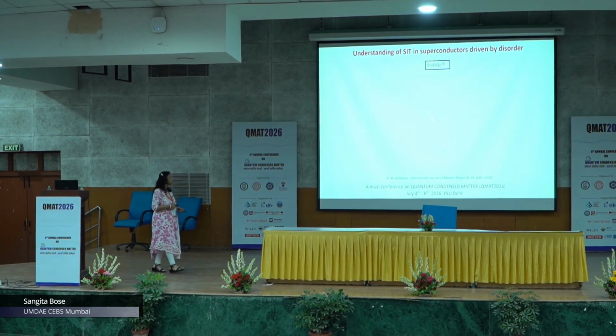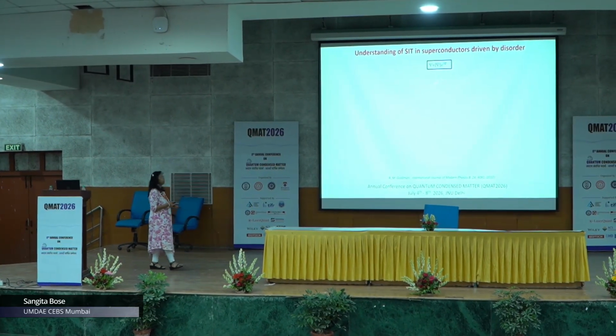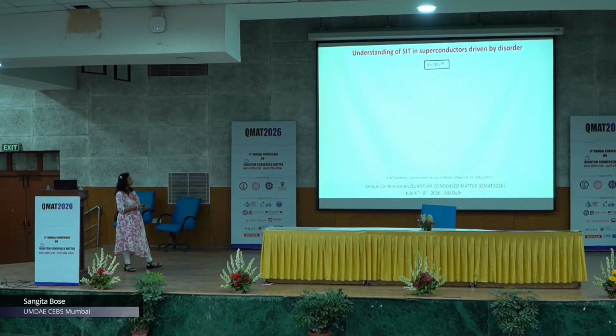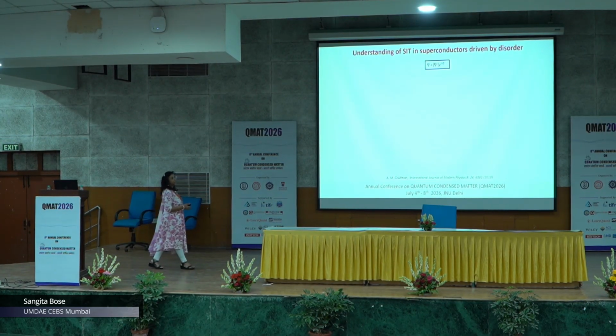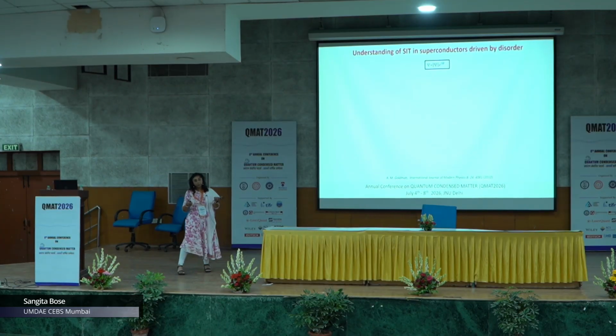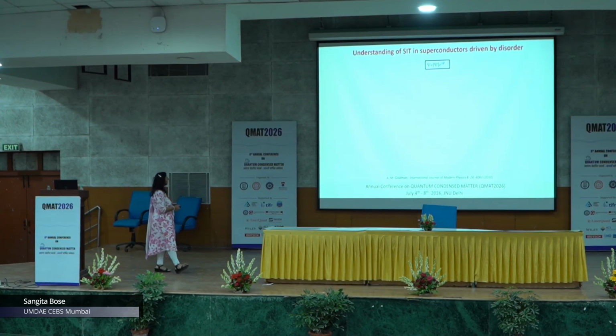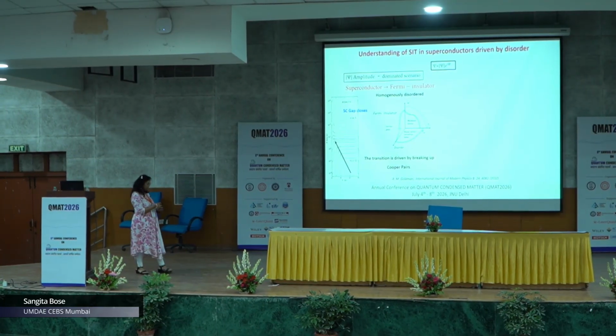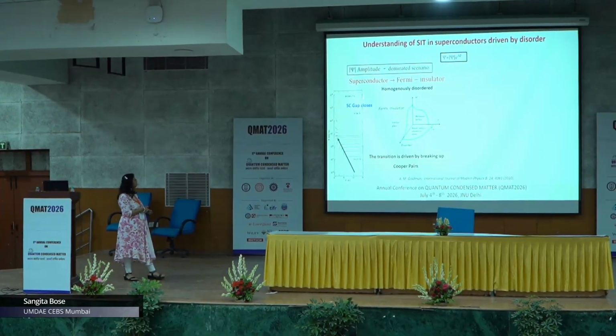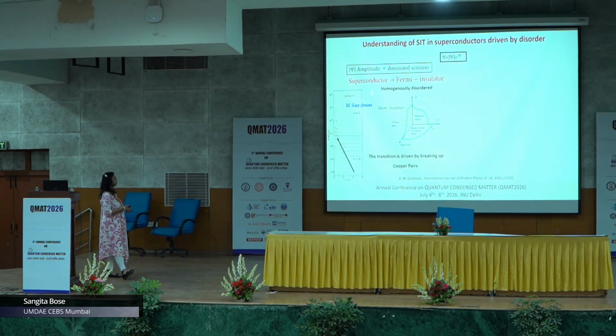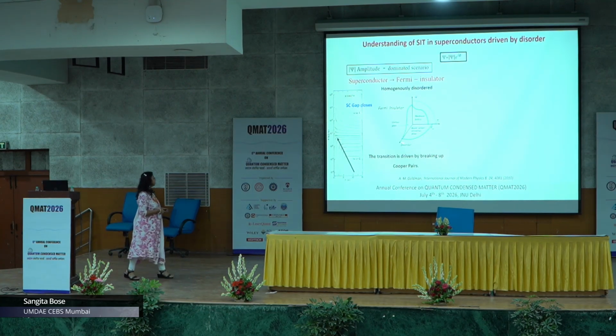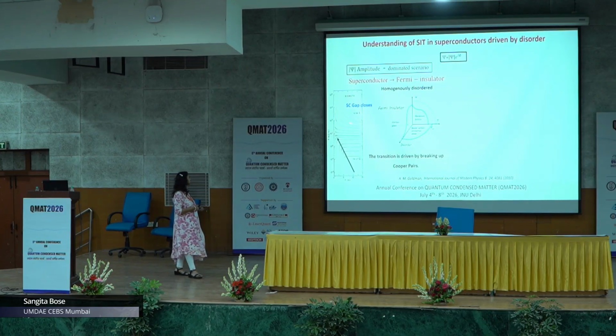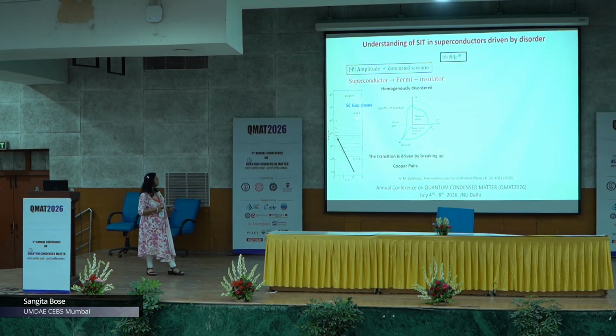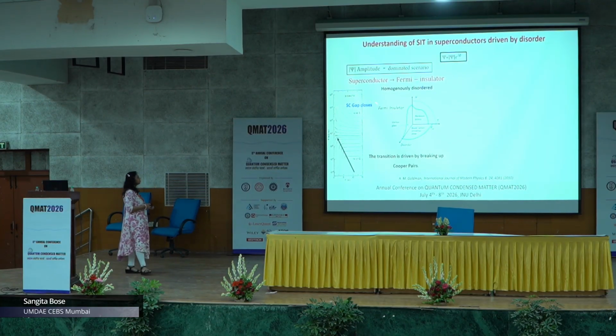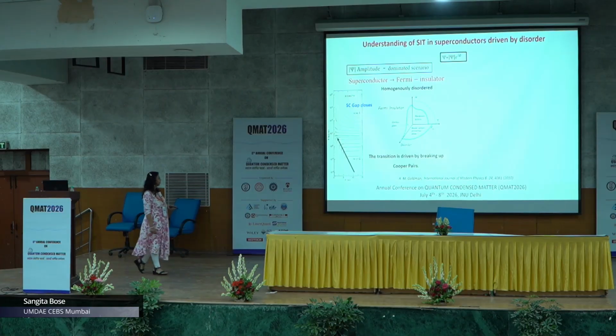For students who don't know, superconductors are governed by an amplitude as well as a phase. Understanding the SIT is actually done by two competing models. The first one is basically an amplitude-dominated scenario, where it is assumed that you go from a superconductor to a Fermi insulator phase, and the transition is mainly driven by the breaking of the Cooper pairs. Measurements done in the insulating phase of this superconductor-to-insulator transition observed that the superconducting energy gap closes in this scenario.